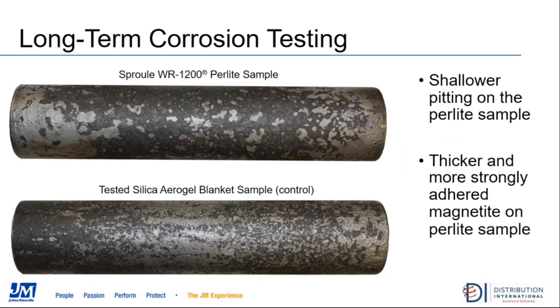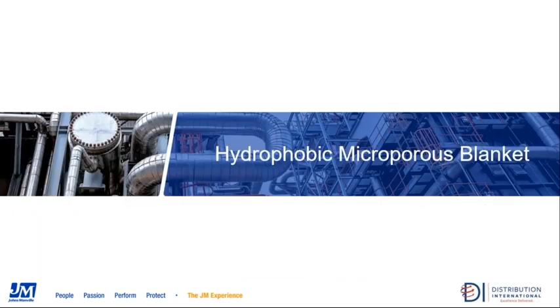Similar picture to what we just saw with Sproule WR-1200. Again, this is compared with silica aerogel, and the results were the same on this long-term testing. The pitting was much shallower, significantly shallower with perlite than we found with silica aerogel. And again, the pitting is the loss in wall thickness due to corrosion.